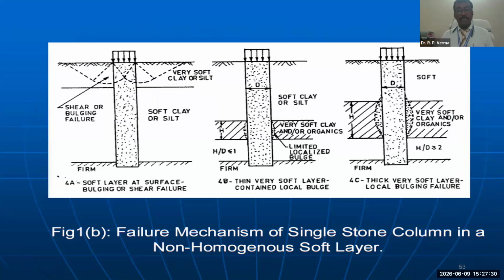When we deal with complex, non-homogeneous, stratified profiles, the failure mechanism changes, as classified in figure 1b. If a soft layer sits right at the surface, we see a combination of sharp bulging and shallow shear failure. If there is a thin, ultra soft layer embedded deep down, it creates a highly contained localized bulge. However, if that ultra soft clay or organic layer is thick, a massive localized bulging failure occurs.